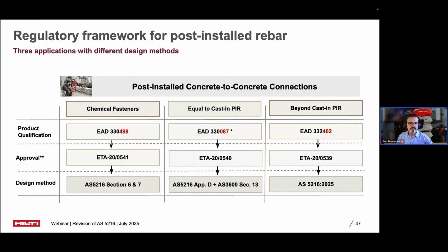And the new post-install design method, which is the beyond cast-in design method, utilizes the enhanced design method in the AS 5216 2025 revision with a new EAD qualification, which requires another ETA. So as an example, for RE500V4 that has been approved for this system, we have 3 different ETAs because it has been approved for different applications. So it can be used as a chemical anchor. It can be used as a post-install rebar with the equal to cast-in rebar design method, or it can be used again for post-install rebar applications with the beyond cast-in, the new design method in AS 5216.